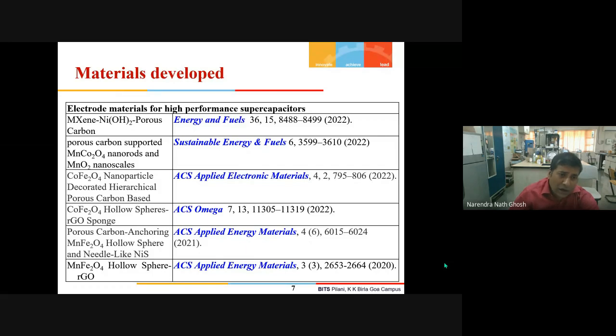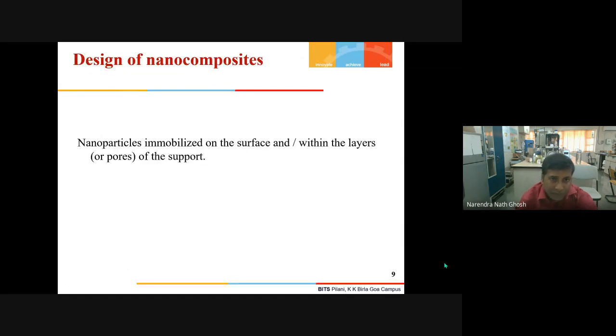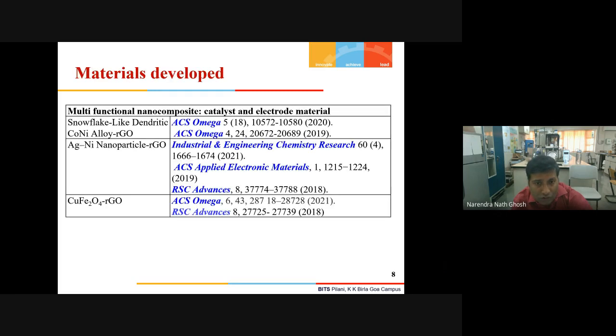Then we have embedded manganese ferrite hollow spheres and needle-like nickel sulfide within the porous carbon, and manganese ferrite hollow spheres with the reduced graphene oxide. So this material we have used as an electrode material. Next, please. No, I think you have jumped one more.